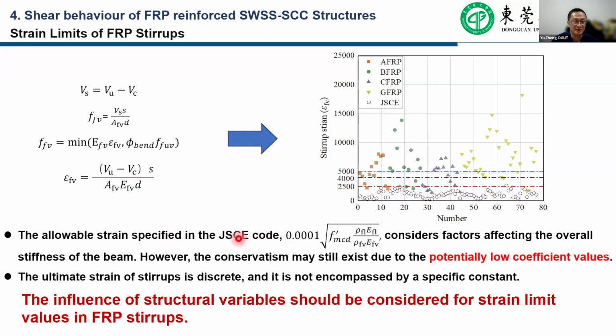We can find that only the JSCE model uses a function to predict the effective strength for the FRP stirrup. However, the prediction accuracy is quite low. It considers the influence factors, but they have not been considered by this model accurately. And furthermore, we can find that the CSA model and the ACI model use a constant value, and the prediction accuracy cannot be acceptable. The influence of the structural variables on the strain limits for the FRP stirrup needs to be studied further.